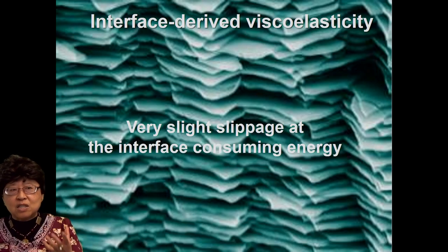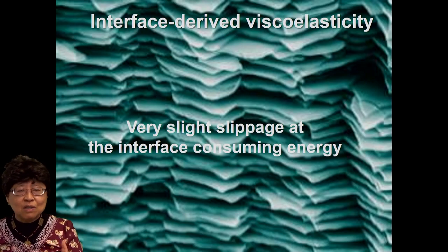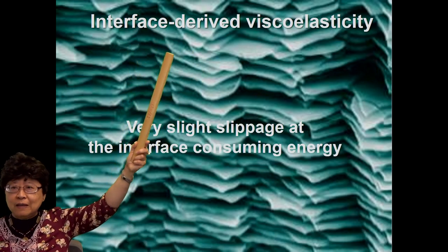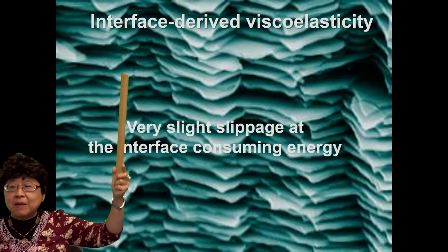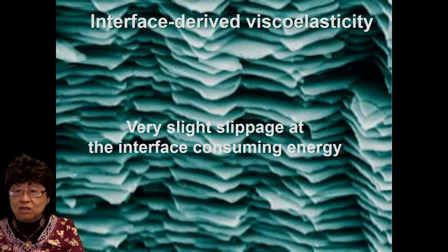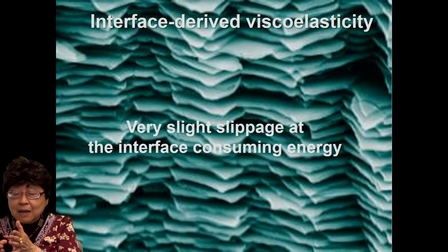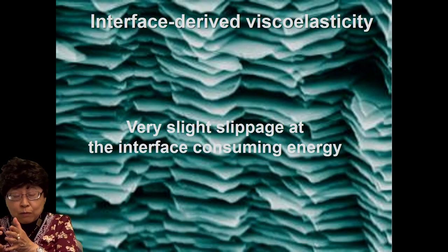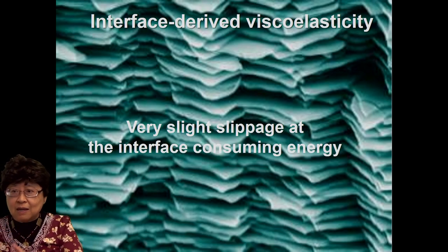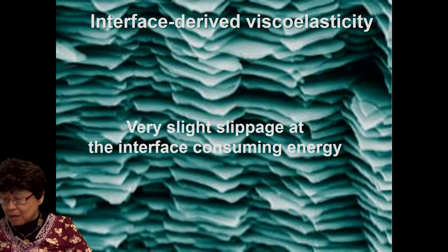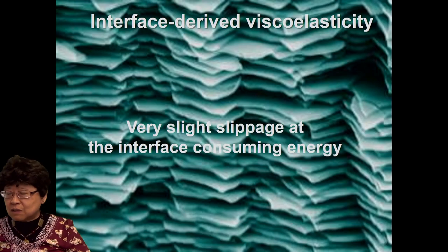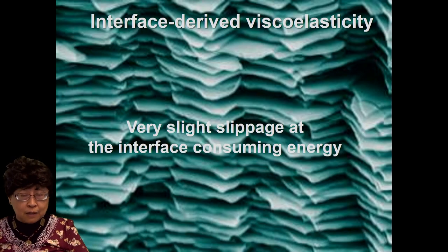And to get a stiff material to be able to have viscoelastic character, one needs new science. Okay? And I have pioneered this new field, which uses interfaces in a material to provide energy dissipation. Because very slight slippage at the interface, with friction involved in the slippage, would consume the mechanical energy. I call this interface-derived viscoelasticity. But for this to be appreciable, you need to have a lot of interfaces.